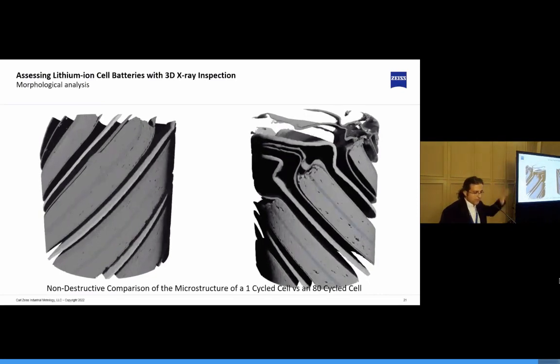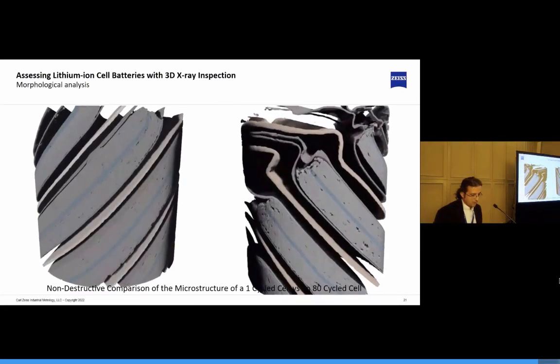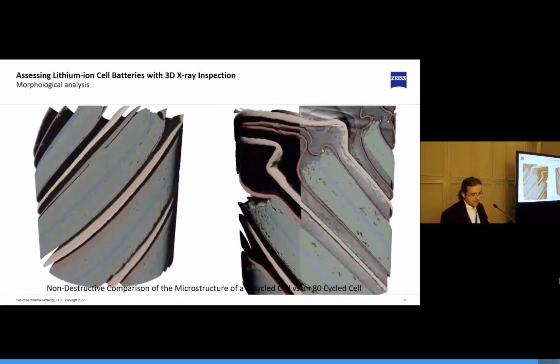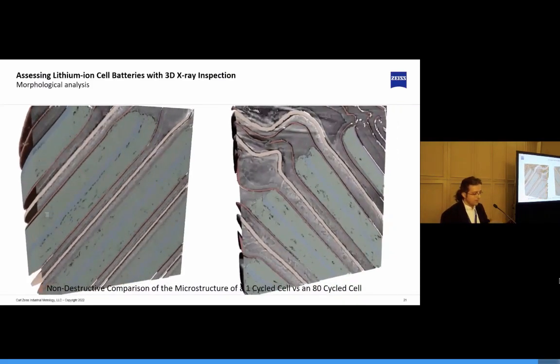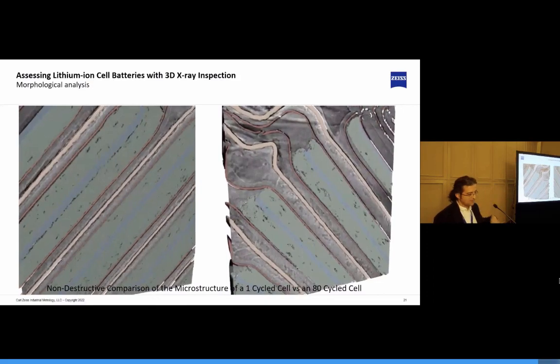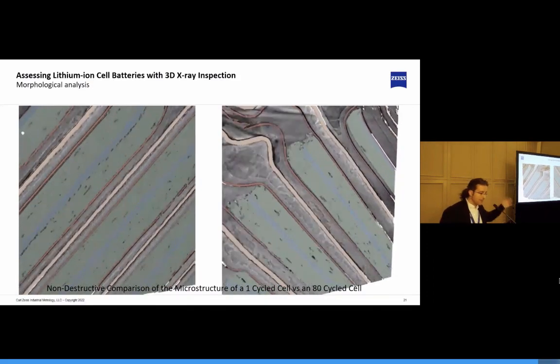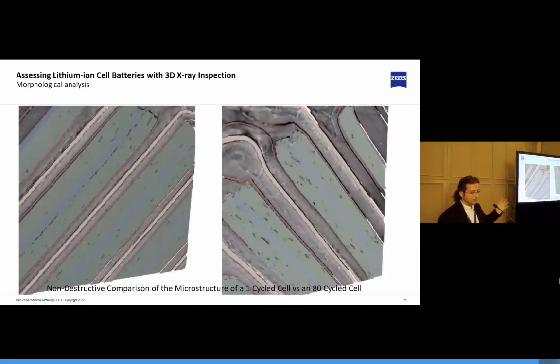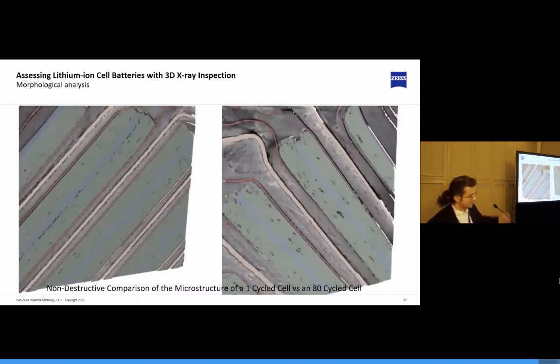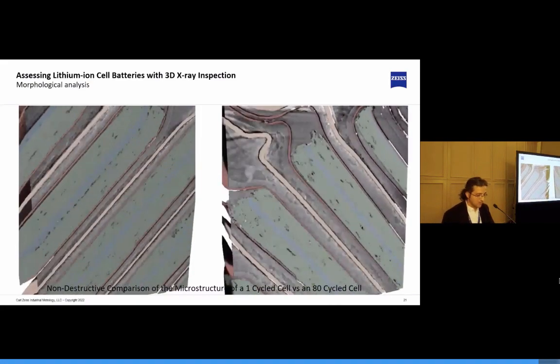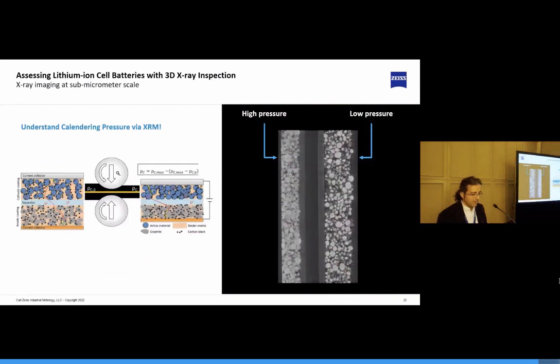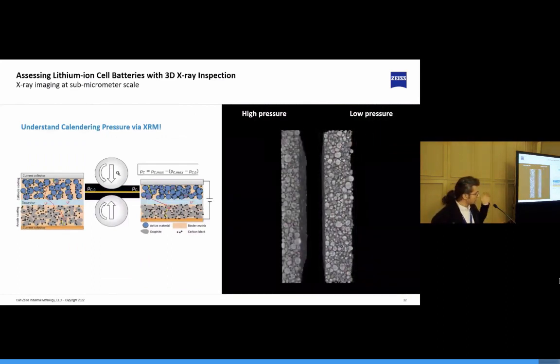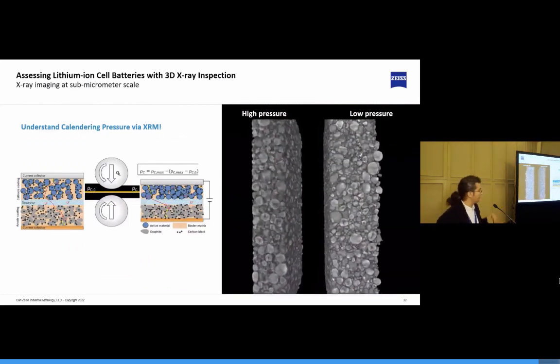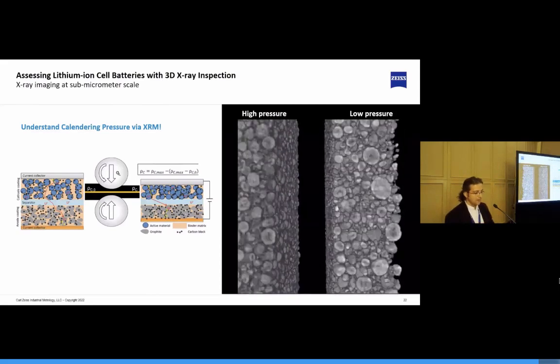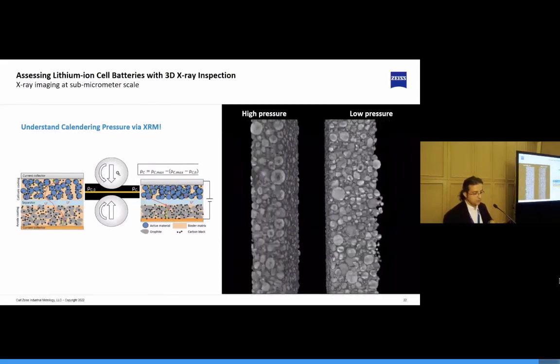And you can do other types of studies. It's not only about aging. Well, yeah, certainly aging, but you can see some morphological deformation in the edges of the electrodes, stress formation, some variation of the radial distance, and separation of the different interlayers of the battery, which is certainly very important for you. And we can also check the outcome of poor mixing and weak battery compaction process.